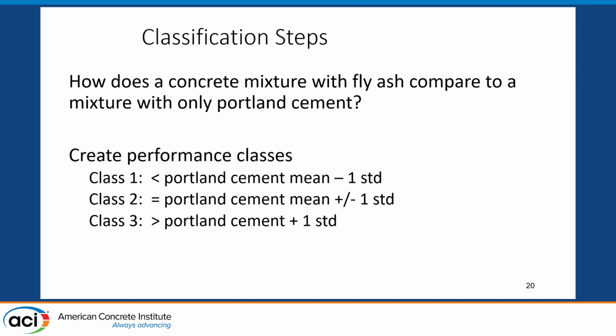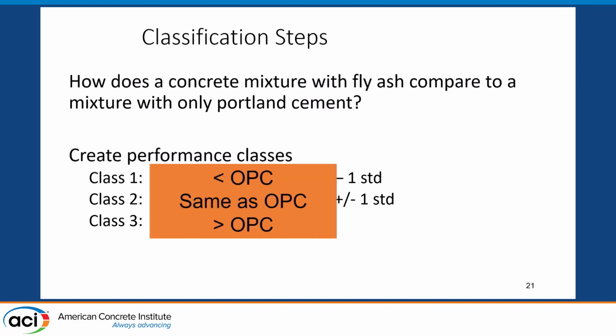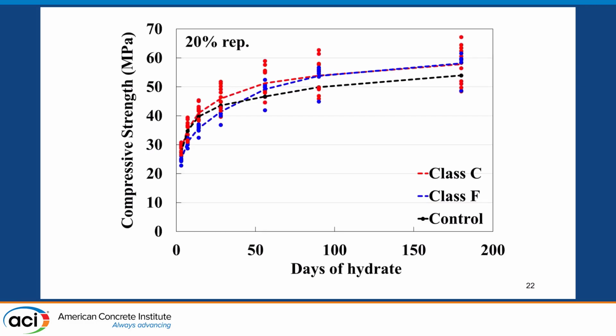It makes it easier to compare one fly ash to another. Basically, if you don't understand what I'm talking about, Class 1 would be less than OPC, Class 2 would be about the same, and Class 3 would be a better performance. And I'm talking about data like this. Here is strength on the y-axis. Here is days of hydration. The black line there is Portland cement. The red line is Class C ash and the blue line is Class F ash.